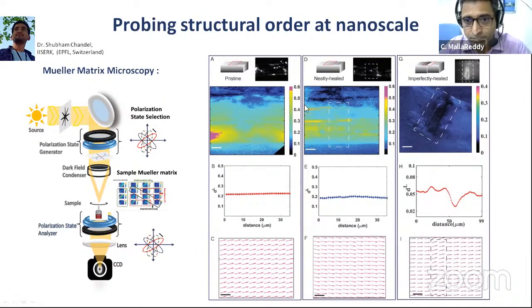We looked at pristine crystals, neatly healed crystals, and imperfectly healed crystals. We found that neatly healed crystals are about 10 to 15 to 20% lower in terms of order compared to the pristine crystals. So pristine are the best, and neatly healed crystals have at least 10 to 20% lower order. But for imperfectly healed crystals, especially in the area where you have a crack, there is about a 50% drop. So this allowed us to quantify, but in X-ray we could not find any difference between these two.